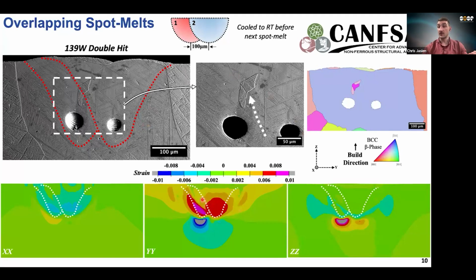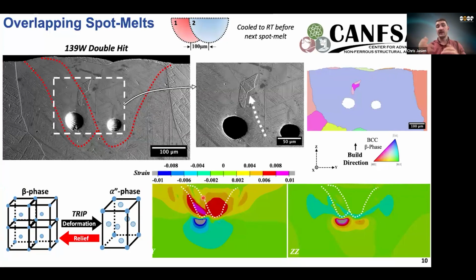As we move up along this corresponding boundary, we can see a reduction in the magnitude of the strains. So thus showing us that this is a process where as we heat it up to intermediate temperatures, we can actually cause it to go back into its other phase. So essentially, mechanistically, what happens is we initially start with the beta phase, and because of that transformation, we get this alpha double prime phase, which we saw in the previous materials.